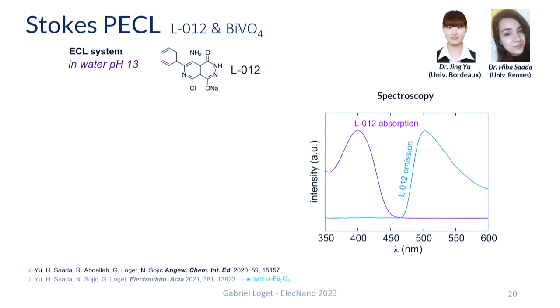And this work has been done by former PhD students, Jing Yu in Bordeaux and Hiba in Rennes. They work with this other electrolyte, which contains a luminol analog called L012, in alkaline medium. And here you can see the spectral data for this electrolyte. We see that the luminophore absorbs below approximately 450 nanometers, and the luminescence occurs with a maximum at about 500 nanometers.